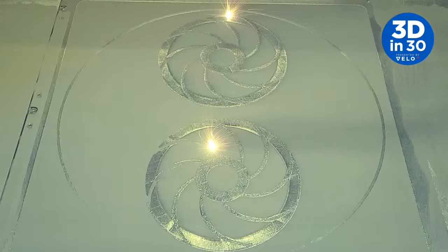Then if you look behind it, you can see this sort of black cloud that's coming out. And that is the soot, which is one of the byproducts that happens when you are lasing the metal powder. And basically, if you have this black cloud, and you don't get it out of the way fast enough, it'll interfere with the incoming optical energy, which can cause issues with the beam in terms of blurring, scattering or loss of power, which then changes how much energy you're actually getting into your liquid melt pool, which will then cause your process to shift and oftentimes can cause defects. So it's really critical. That black cloud is basically one of the big things that you're trying to get out of the system with the gas flow.